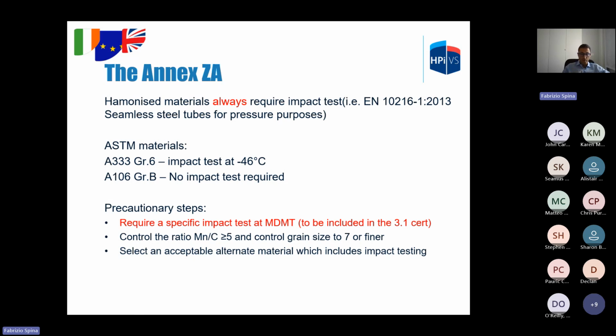The ASME code and the EN standards take fundamentally different approaches to use at low temperature. The ASME code relies on historical experience of safe use, so it accepts a small percentage of risk, as materials in the standard are usually specified with a range of chemical composition and mechanical properties. This variability can lead to differences in performance at low temperature. So we could have a good steel or a bad steel. So the history of safe use doesn't guarantee that this material can have good properties at low temperature. So, summarizing, impact testing is always required for carbon steel material for use below 0.